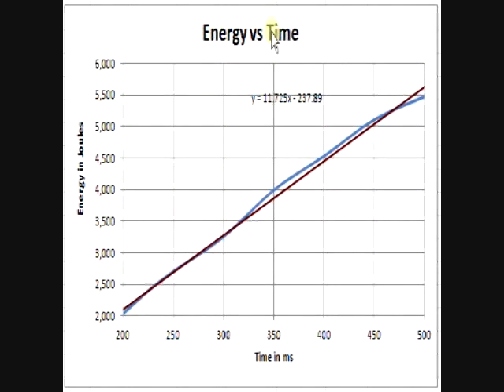This is the energy versus time plot while the current is constant. This is the energy in joules, and this x-axis is time in milliseconds. You notice I did not plot any expulsion weld because I couldn't measure the expulsion weld anyway. And the blue line is the real curve.